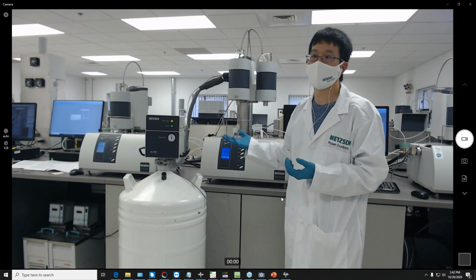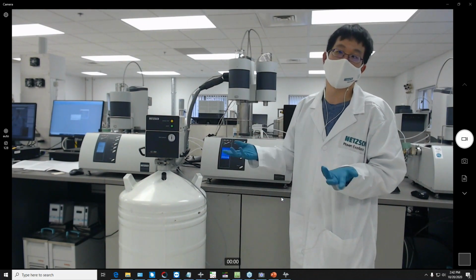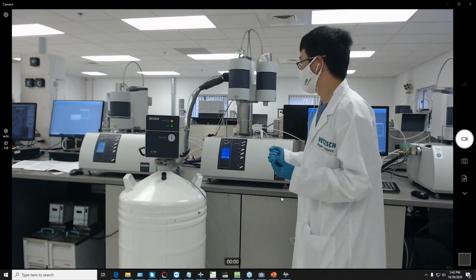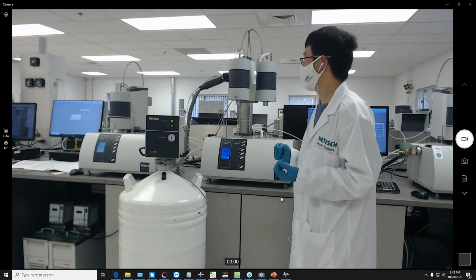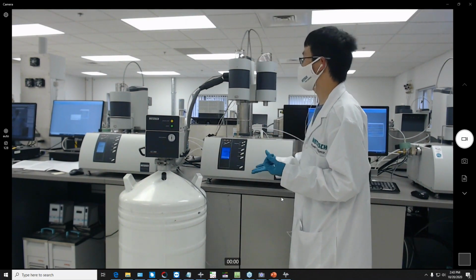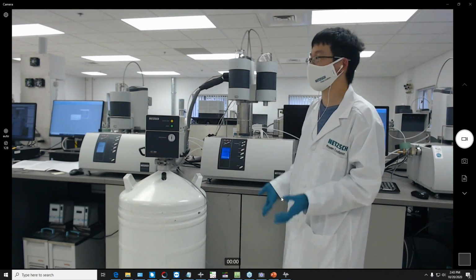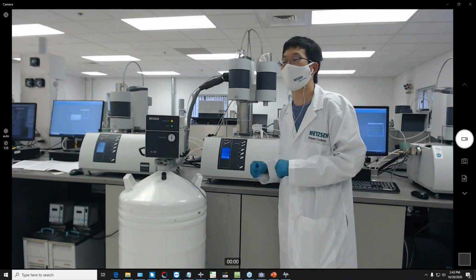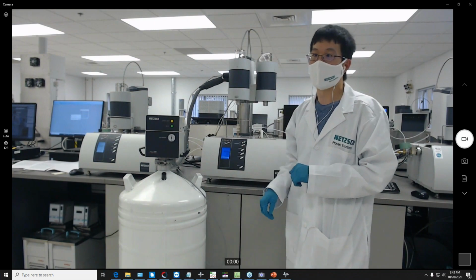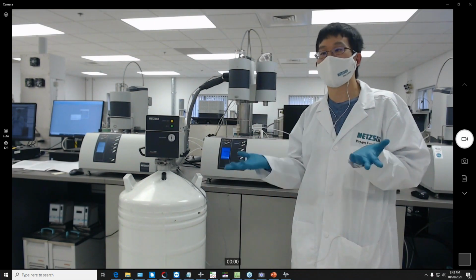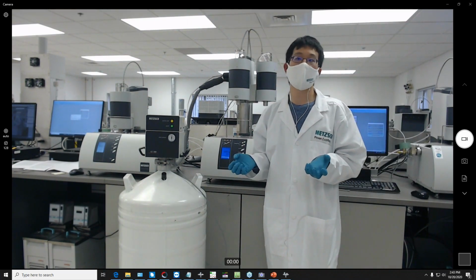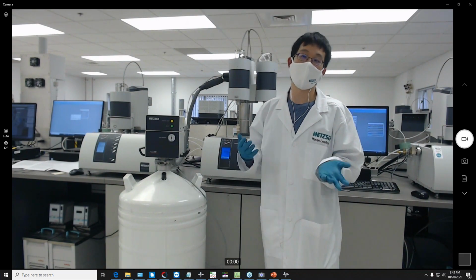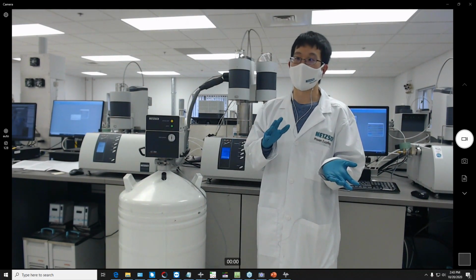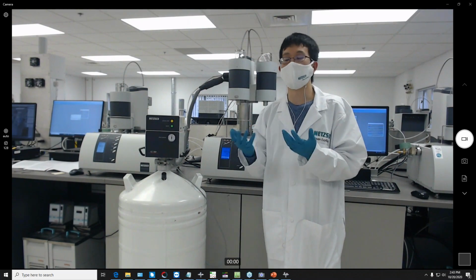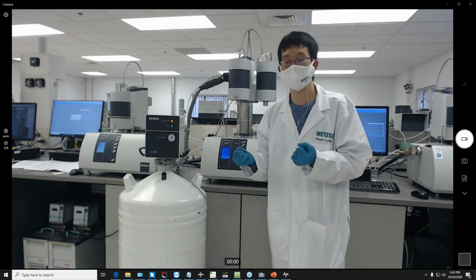And then the remainder 50 can be in purge 1 or purge 2 or a mixture of them. So this is just to allow sufficient flow so that any evolved gases from your sample can be pushed up out the exhaust at the top. For specific other types of measurements, there are abilities to increase or decrease the flow, so it really depends on what you're after.